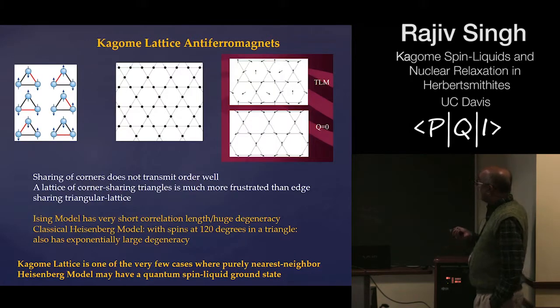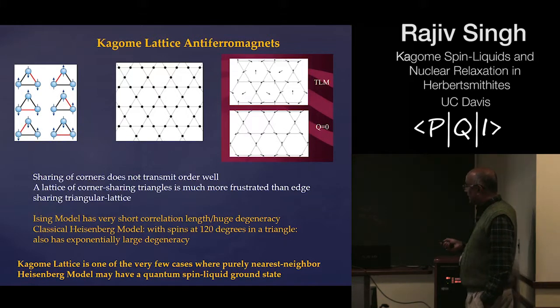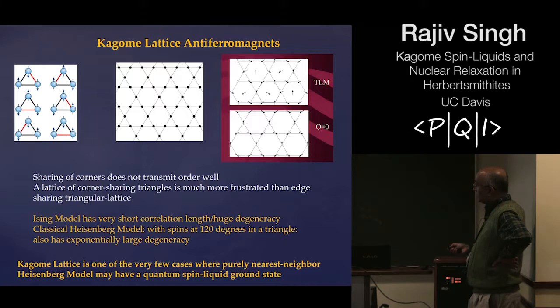Okay, so what is this Kagome antiferromagnet? The Kagome lattice is basically a lattice of corner sharing triangles, and triangles have this property that if we consider, for example, a spin-half Ising model, it can take two possible values at each lattice site, and that means the triangle can take 8 possible configurations, but 6 out of the 8 are actually ground states. They are the lowest energy. Only the configurations where all are up or all are down are not a ground state. So a huge degeneracy is a general feature of frustrated magnets, really.